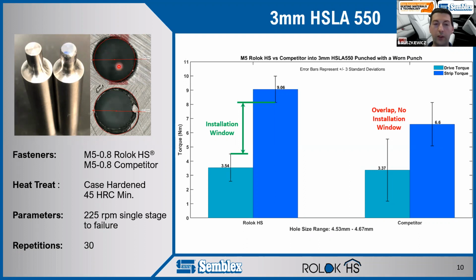There's two pictures of a hole to the right of that. These are from the worn punch. The top picture is the punch entry side, so that's where the punch initially contacted the steel. The bottom is the punch exit, and you can see how nasty this looks. It's very blown out. There's actually a lot of cold working in here, and it's going to be very hard at this interface. This is the side of the joint that we drove the screws through because that's where our customer was having the problems.